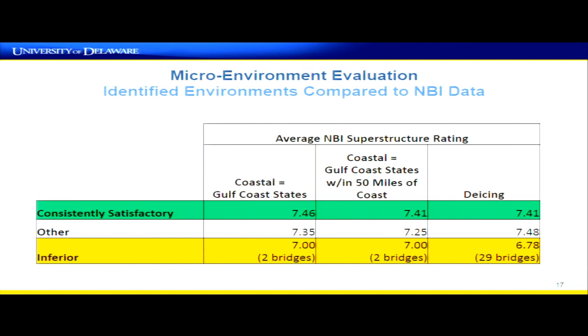And look at the average NBI ratings of the bridges that fall into those consistently satisfactory or consistently inferior categories, or what else is left. If we look at the coastal, it looks like those conclusions are pretty good. The consistently satisfactory bridges have a higher average NBI rating than the ones that were in neither category, which have a higher rating than the ones in the inferior category. So that's some support for those findings.